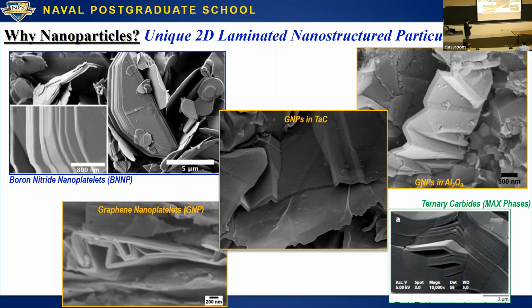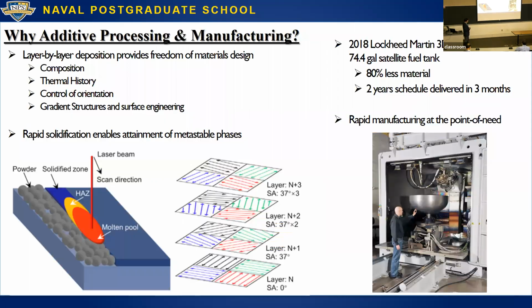These were actually just nanoplatelets alone without any composite. And you can see individual sheets bending. This is kind of the ideal behavior that we would want when reinforcing a ceramic, right? A hard, stiff material that's able to deform, that allows you to absorb strain energies that would otherwise go into fracture. And so that's one of the reasons why these are really good candidate materials for using in composites. So what about the additive part?